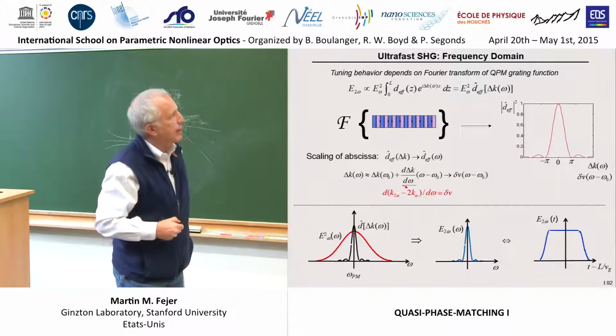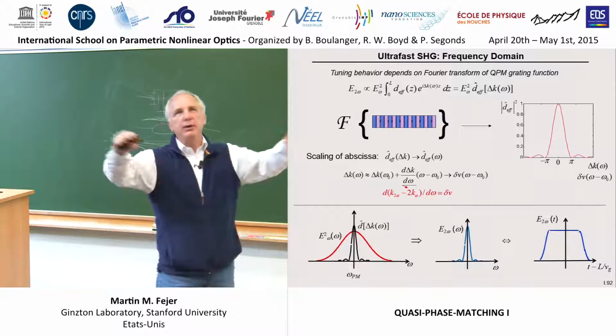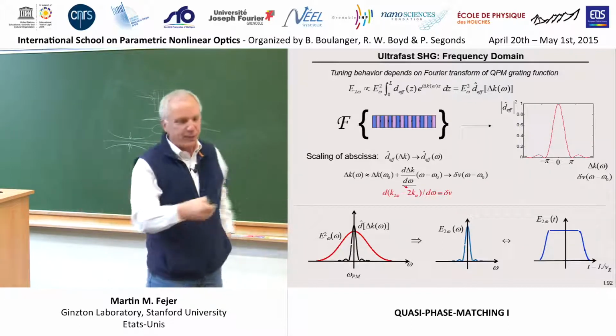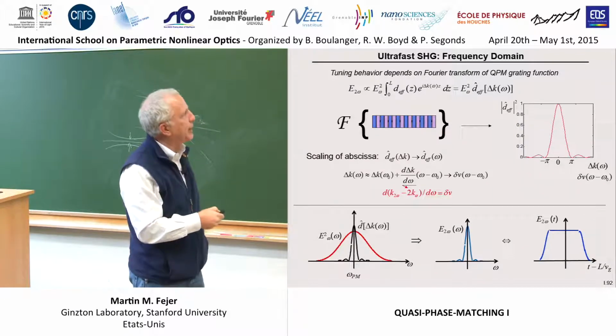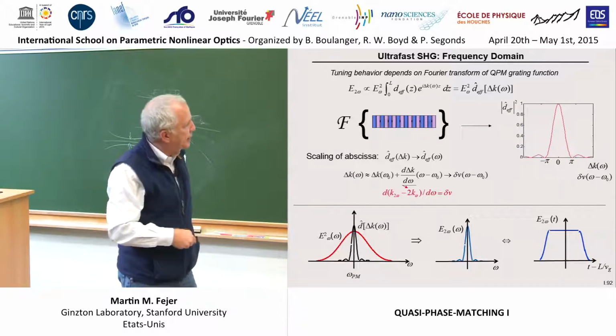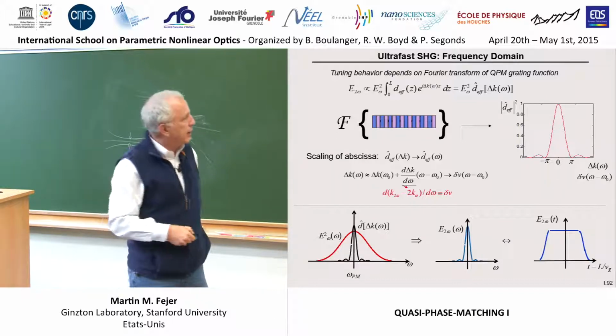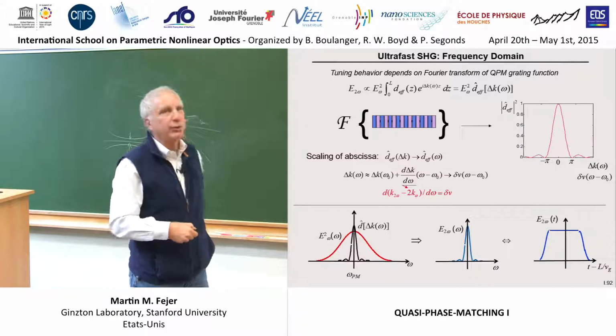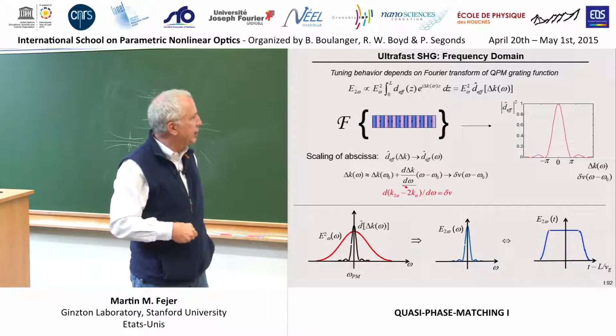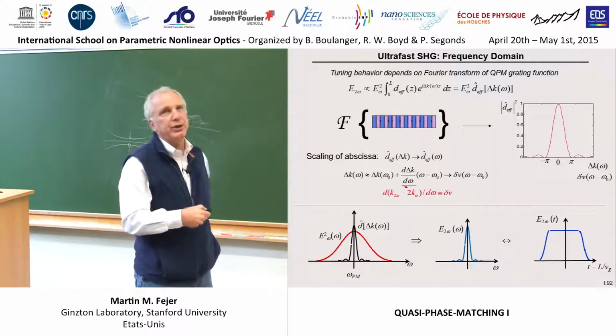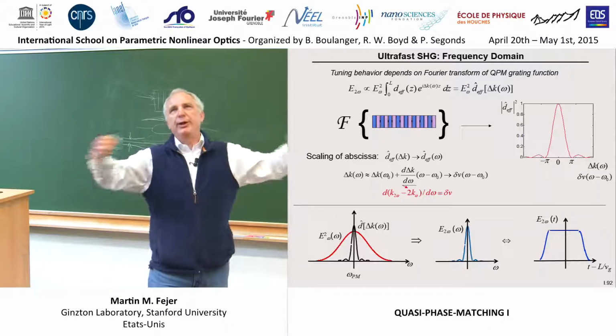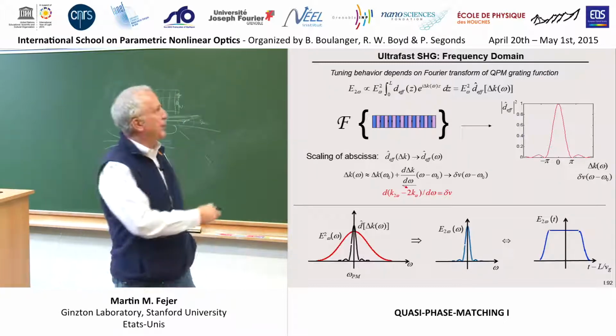if it's not a simple periodic grating. We could engineer a different passband for our crystal by, say, chirping this grating, and we could still make this filter argument. But now, of course, the thing we generate will look very different because we have altered the transfer function of our chip through the domain engineering that we do to change this Fourier transform.